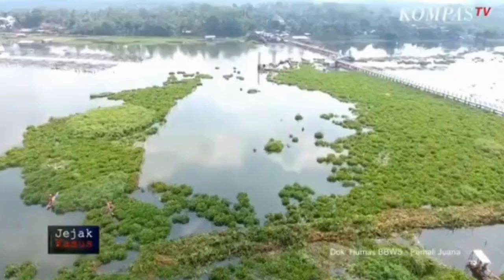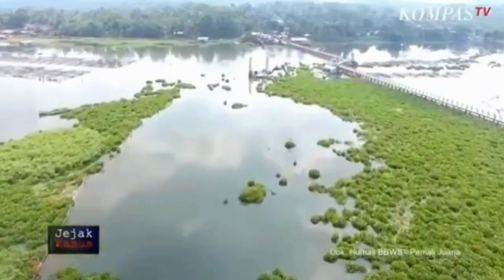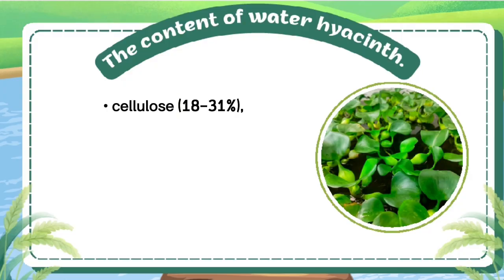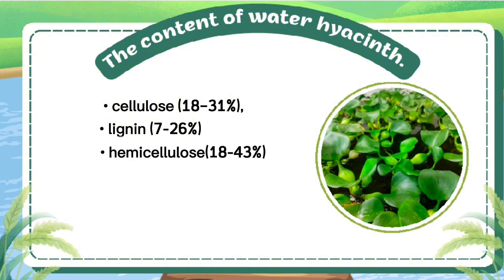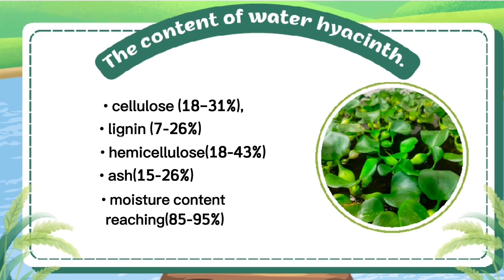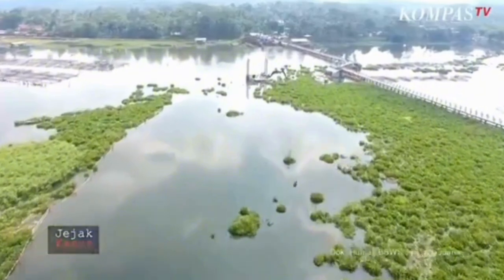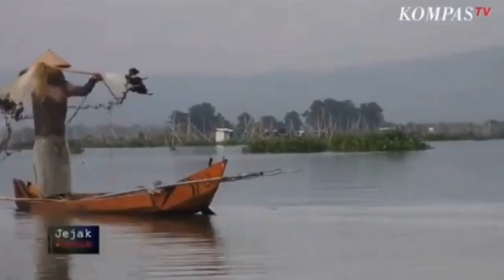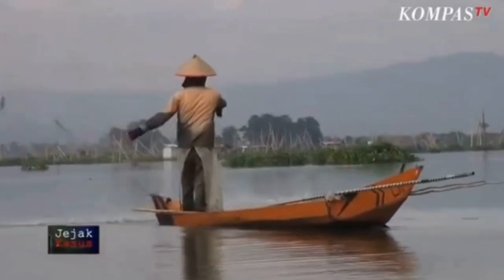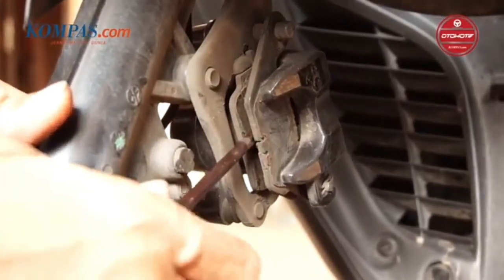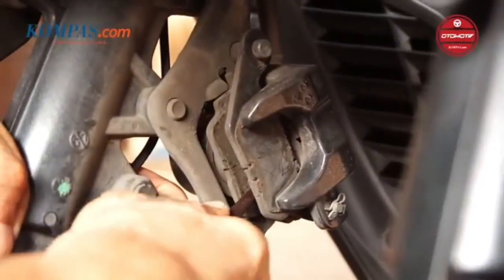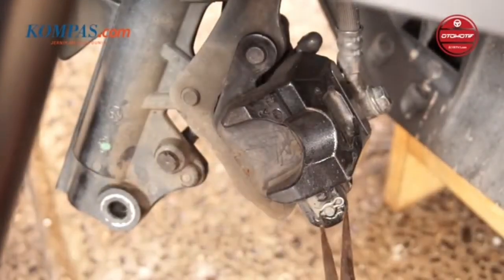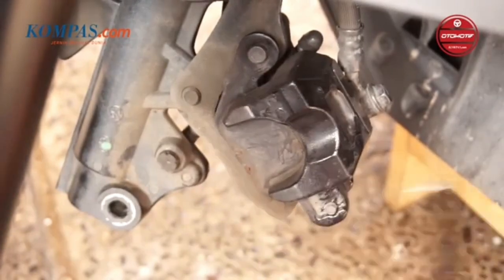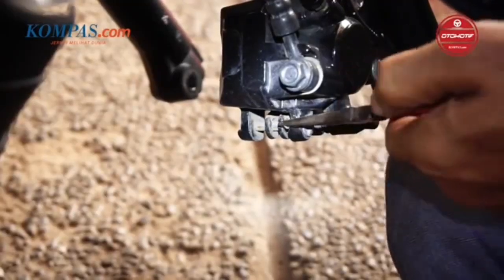We chose water hyacinth as a filler material in this composite due to its chemical composition, which includes cellulose 18 to 31%, lignin 7 to 26%, hemicellulose 18 to 42%, and ash 15 to 26%, with a moisture content reaching 85 to 95%. The relatively high cellulose content in water hyacinth serves as a reinforcing agent in the production of this composite. Seeing the issue before, this research proposed an innovative brake pad made of composite material utilizing water hyacinth fiber and glass powder as filler, reinforced with an epoxy resin matrix.